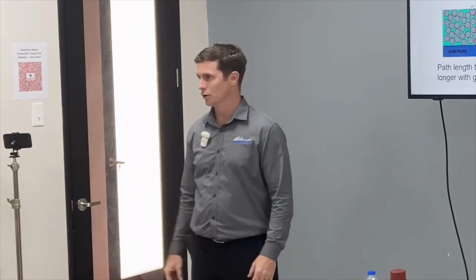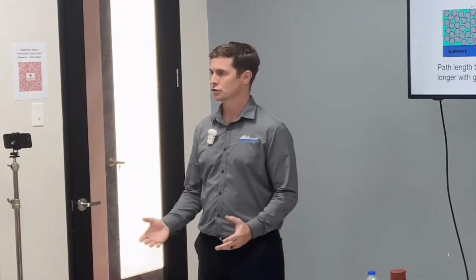And there's adhesion promoters that we can use for FRP pipes that may or may not require sandblasting, which is always preferable. So we can get really good adhesion with these adhesion promoters and put a barrier coat on top of that. As far as the strength, I think you're probably referring to tensile strength.